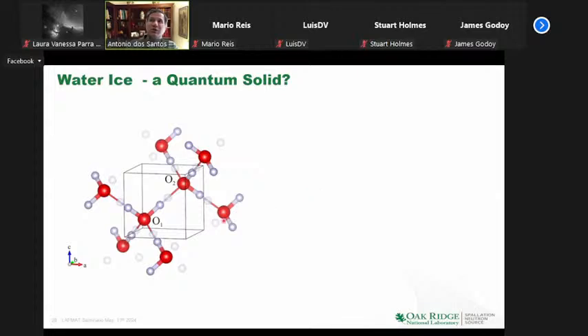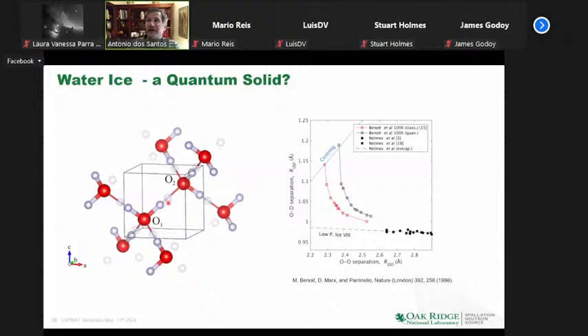And what we're looking for with increasing pressure is, is there a point where the hydrogen stays in the middle of the bond and water becomes essentially an ionic solid? It has a name, it's called ice X. It's never been observed in the lab yet. There have been calculations, and this is just a contrast. If you consider a purely classical or a quantum system, where would the centering happen as a function of essentially pressure? And these were the prior known structures of water.